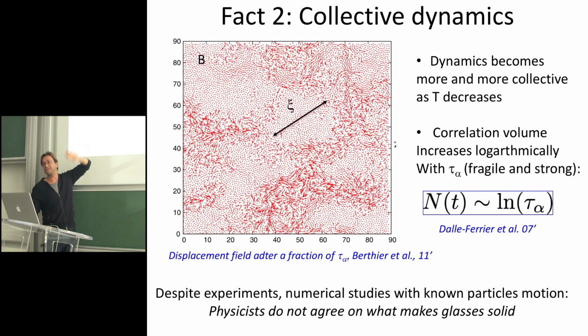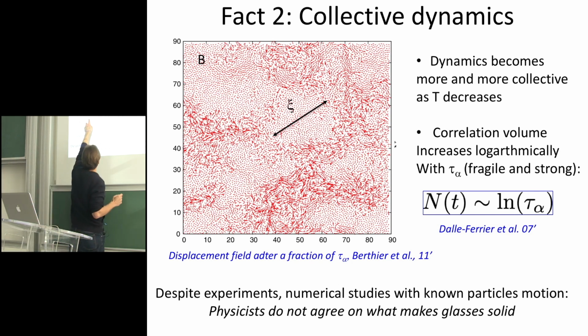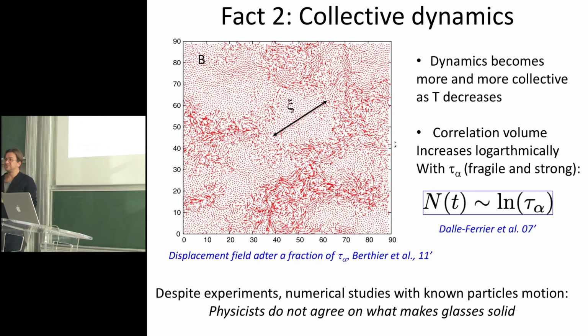You can simulate liquids, not on 15 decades. And what is shown here is just the motion of the particles on the time scale, which is of order of this tau alpha. And what you find is that you have big patches where almost nothing happened. So it was still, if you want, a solid there, but other regions where it did relax. Okay, so you would really like to also understand those dynamical heterogeneities.